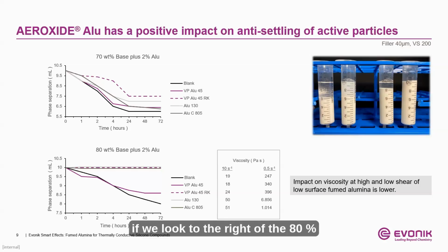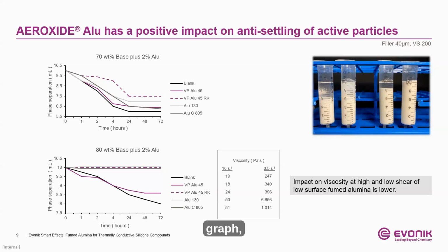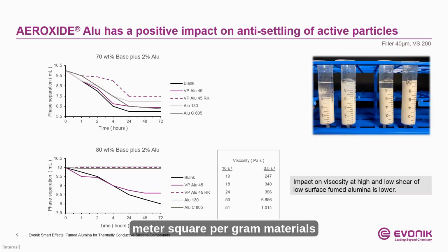Lastly here, if we look to the right of the 80% graph, we see high and low shear viscosity of the materials. Most noticeably, the similar viscosity of the 45 meters squared per gram materials to the blank containing only spherical alumina. With the higher BET materials, you tend to get better separation control from modifying the overall viscosity, but the benefits of the VP Alu-45 RK hydrophobic treatment are again seen by creating separation control in the system while maintaining a